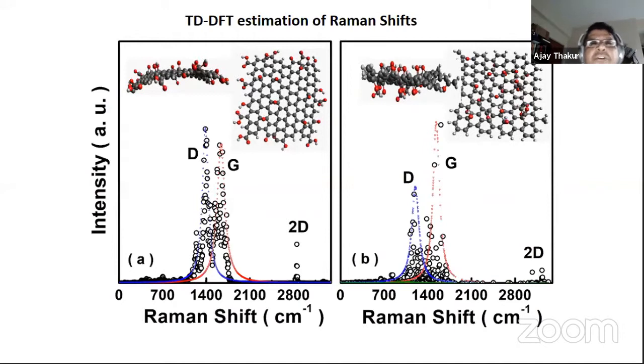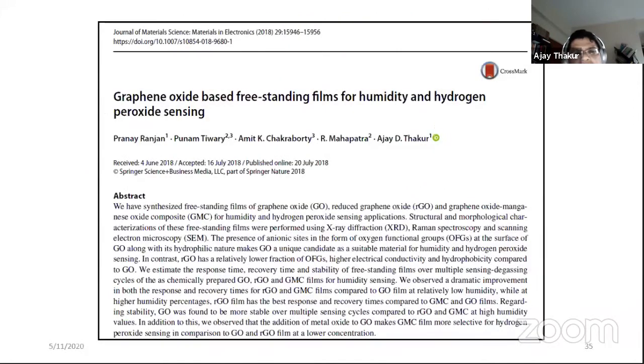And one can compare this with the kind of pictures which we generated using atomic force microscopy. Okay, we also went on to do DFT estimation of Raman shifts. What we observed is, based on the functional groups which we could see using FTIR spectroscopy, if we attached such functional groups to the carbon base layer, we could generate intensities around the D, G, and 2D locations. And as you can see in the next figure, for slightly different combinations, this peak structure is totally changed. So we also tried to make a connection with being able to simulate the experimentally observed data.